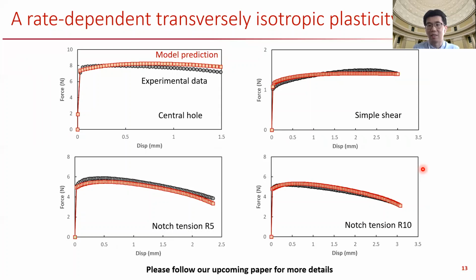Besides the experimental data I showed today, we also did very careful theoretical and numerical modeling of pure lithium. And we find that the material is not only rate dependent, it's also anisotropic, but in the in-plane direction, it is isotropic. So we developed a rate-dependent transversely isotropic plasticity model. Time is very limited today, so I only show you the result. Our model can almost perfectly predict the trend and the magnitude of each curve of the four complex tests. Okay, if you are interested in our modeling, please follow our upcoming paper for more details. Okay,